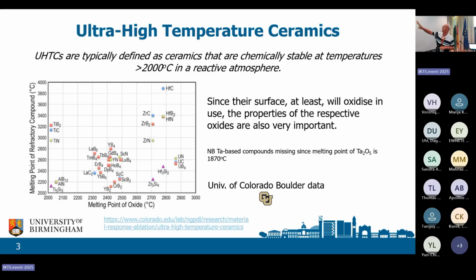The ultra high temperature ceramics are non-oxides. And any non-oxide has a desire to become an oxide at the first opportunity, because oxides are more thermodynamically stable. So you will develop an oxide, and the properties of the oxide are as important as the properties of the non-oxide. Here is a plot of the melting points of the oxide against the melting point of the original material. We're looking for materials in this end, because materials that are up there but down here are potentially going to have a problem.